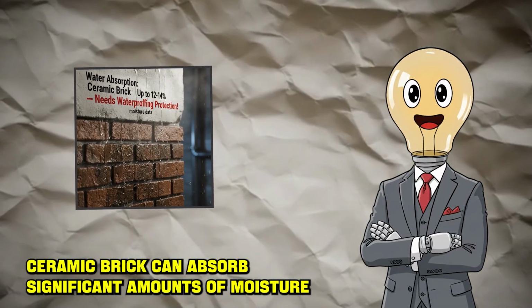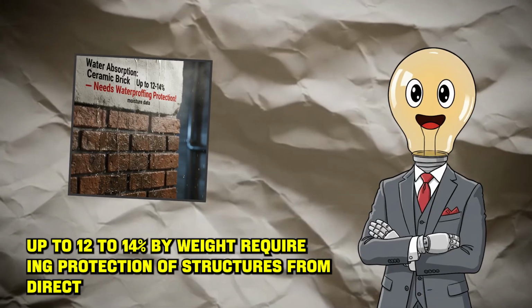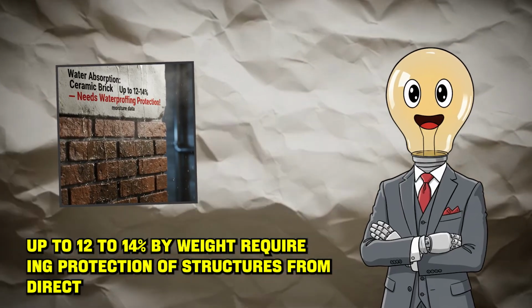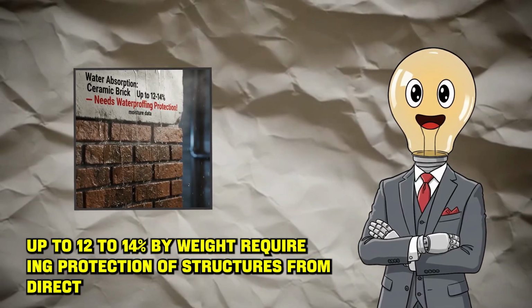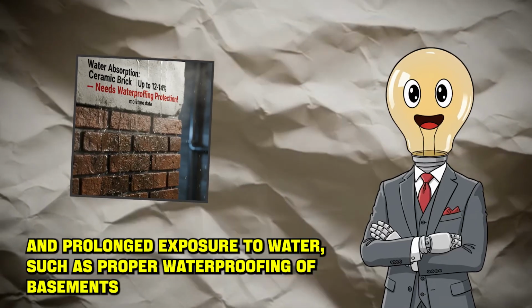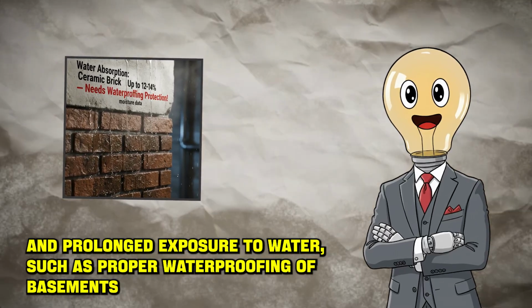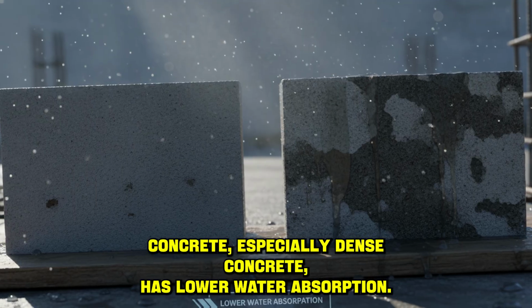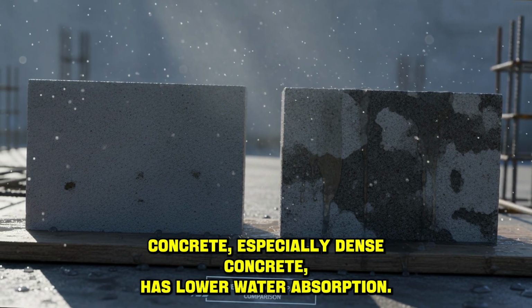Water absorption and vapor permeability. Ceramic brick can absorb significant amounts of moisture, up to 12 to 14% by weight, requiring protection of structures from direct and prolonged exposure to water, such as proper waterproofing of basements and roof overhangs. Concrete, especially dense concrete, has lower water absorption.